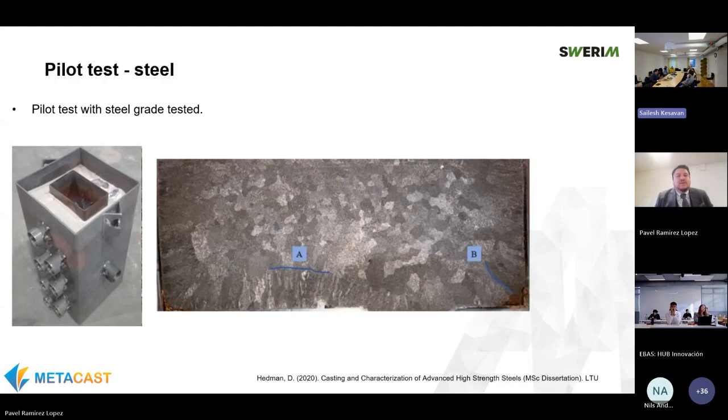And here you can see one of the structures, one of the ingots cut. This is a half cut from what is produced here. And we were so excited to see the classical structures that we observe during continuous casting: a columnar growth from the walls. And then, so now you're familiar with what is a columnar to equiaxed (CET) transition, somewhere here. And then we have an equiaxed region in the center. So we can have a very defined structure that we are looking for.